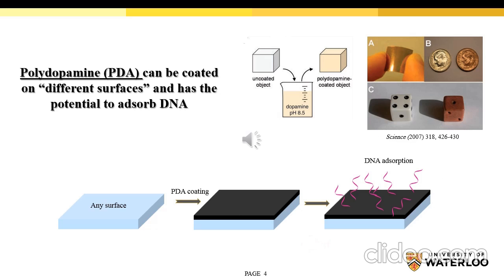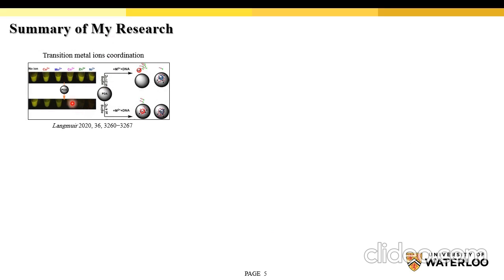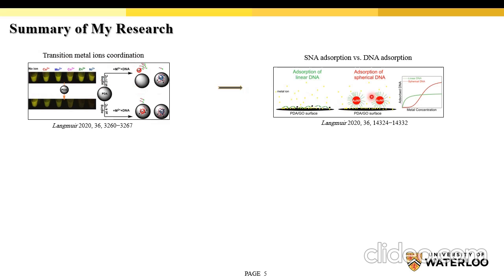To date, we have had good progress investigating interactions of DNA and PDA. We showed that transition metal ions can enhance the DNA absorption efficiency. Using spherical oligonucleotides, we achieved extraordinary stability of DNA absorption on PDA.